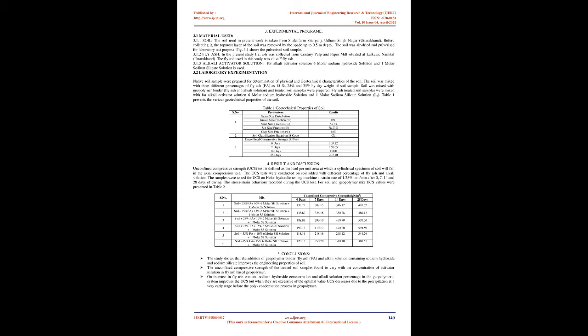In test samples B, weight ratios of 0.3, 0.4, 0.5 and 0.6 of RHA and RM were taken at constant sodium hydroxide solution. In test sample C, 3 concentrations, 2 molar, 4 molar, and 6 molar, of sodium hydroxide were taken at the curing of 60 days, but other parameters were constant.